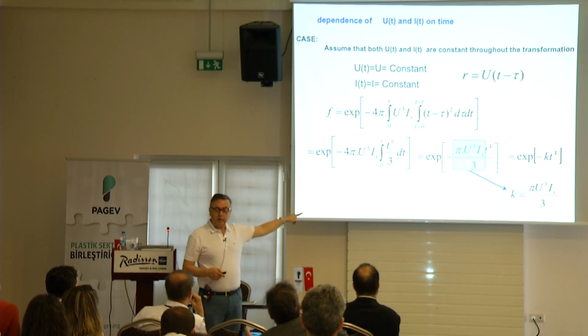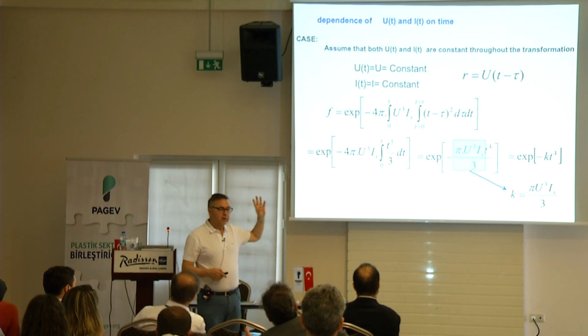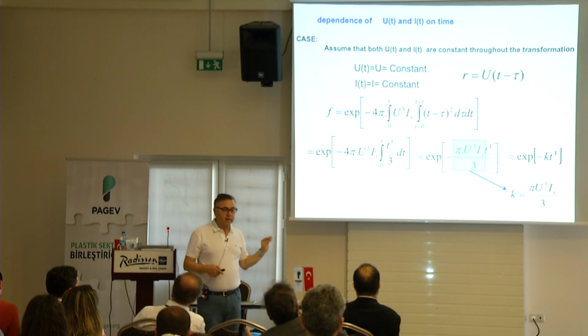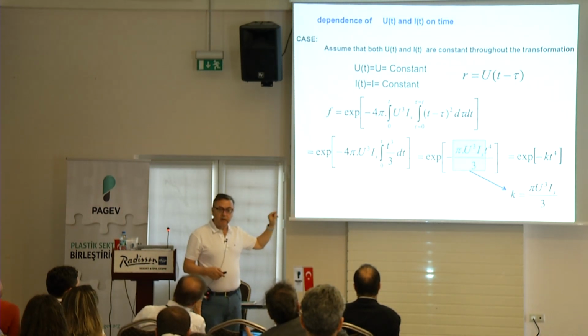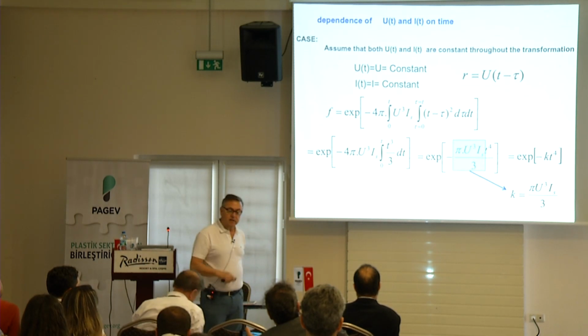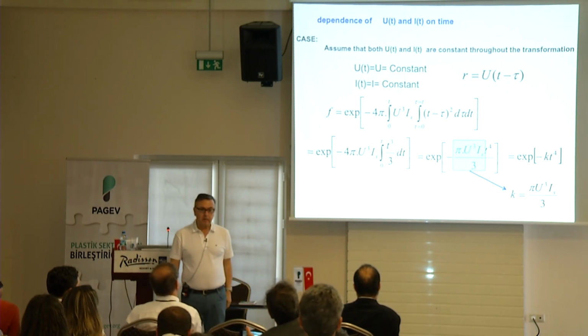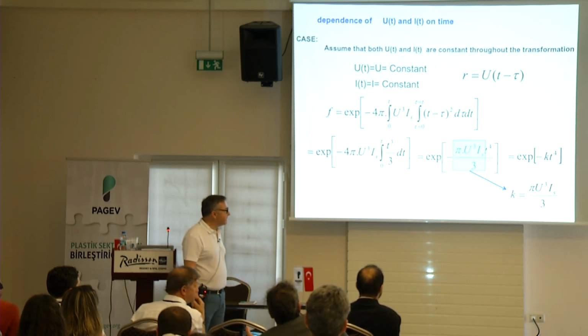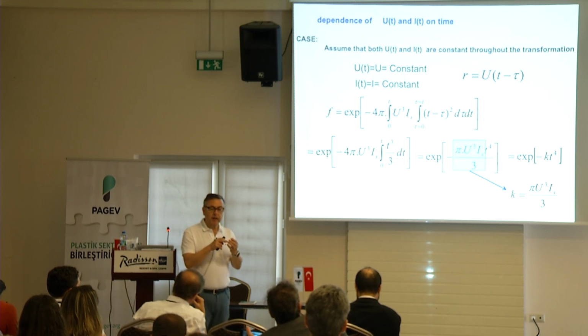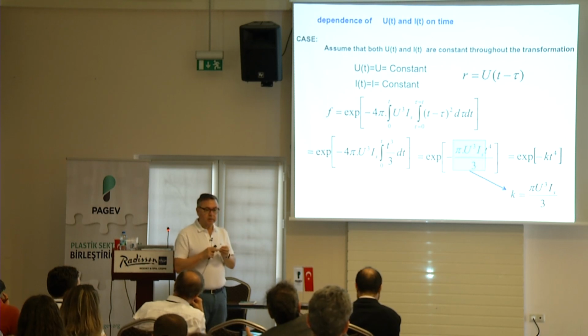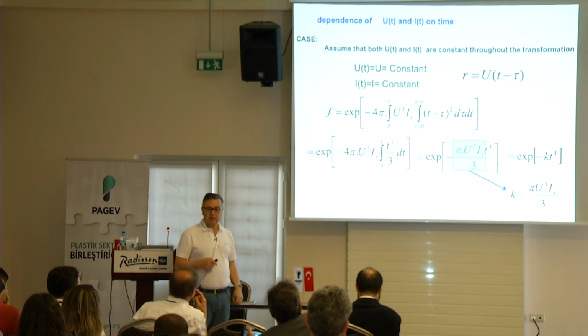And look at the equation. It's the third power, cube. So if you slightly control the growth rate, if you control any of these parameters that control the growth rate, you can directly influence the kinetics of crystallization, right? And this is the nucleation rate, number of nuclei, right? You can add heterogeneous nuclei and so on. But it's the first power.